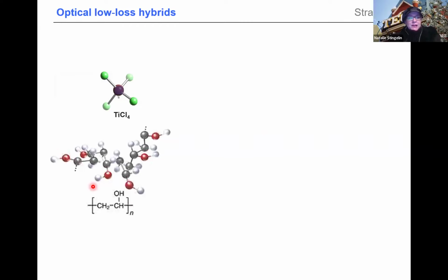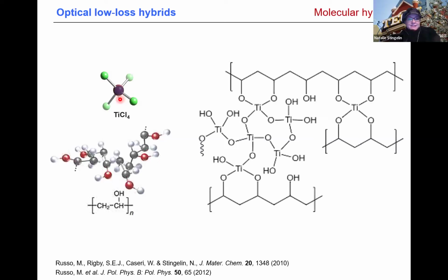It's made out of polyvinyl alcohol, so like polyethylene, but with this hydroxyl group there. And we put them in solution with a titanium dioxide precursor like titanium tetrachloride. You can also use titanium isopropoxide, etc. And what happens is these two react with each other.